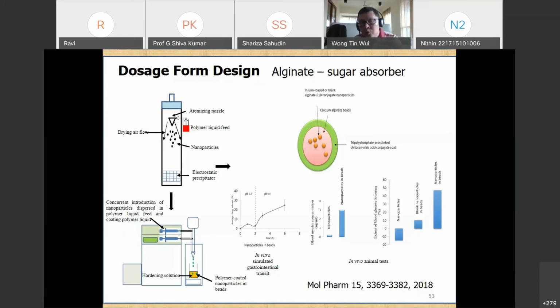Now, in the experiment, we also engage alginate as the encapsulating material for the oral insulin. So we prepared an alginate-C18 conjugate to encapsulate our oral insulin. Now, alginate alone is not used because alginate can interact with the insulin in an excessive manner, to the extent that the insulin cannot be released and cannot even be detected by the instrument. Through designing alginate in the form of an alginate-C18 conjugate, this conjugate is able to encapsulate the insulin, protect it, and yet release it when needed.